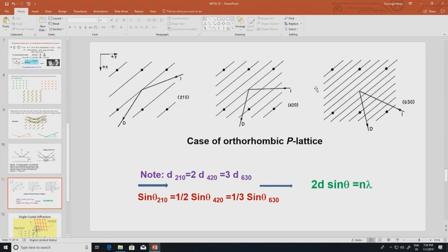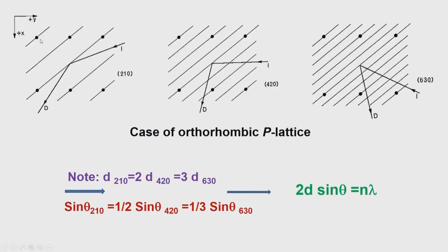When we do the X-ray diffraction experiment, it will individually give the reflections. That means 2d sin theta will be equal to lambda for each one of them separately, because the angle theta is different for each. So, this essentially tells us that the equation 2d sin theta equals n lambda is the one which is covering this. Let me expand this and show what was being said.